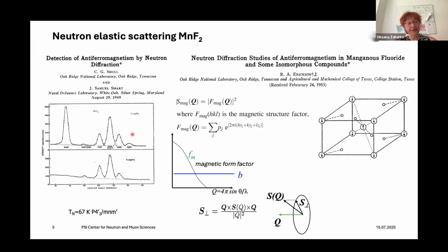If it is a crystal structure, if it is a magnetic structure, I would say a 0.5 by 0.5 by 0.5 millimeter crystal is good, because then I don't have problems with dynamical scattering or systematic errors. Now, if you have a holmium crystal, which has 10 magneton Bohr, or a copper crystal with 1/2 magneton Bohr, that will also scale the size. Also, if you want to see third harmonics or a small canting, probably better to go to a larger crystal.